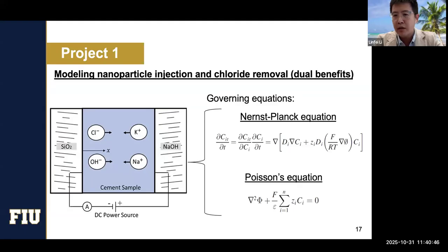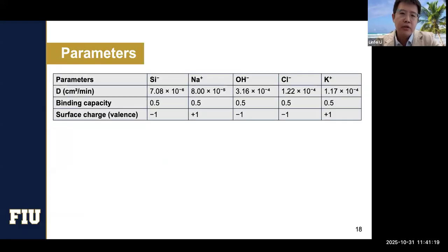The problem is that in this case you have two different variables, the concentration and the electric potential, so you can't solve two variables with one equation. We have to use another equation, so we couple it with Poisson's equation. Now we can solve two different variables using two different equations. We developed a finite element model and solved the coupled equations together. Here are some examples of the parameters we're using. In the system, from the injection head we have the silica ions, nanosilica, and on the other side we're using sodium hydroxide.